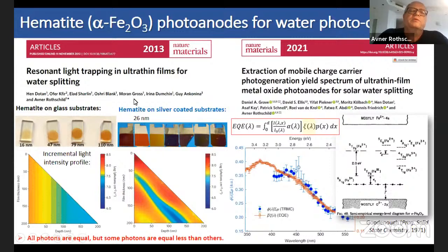So based on this concept, we've been working for nearly 10 years, and still we could not achieve the expected efficiency. The ultimate limit for hematite would give you 12.6 milliamps per centimeter squared under normal sunlight radiation, but we can only get about 4. And no matter what we did, by improving the crystal structure, by adding different selective layers, there is something like a glass ceiling that we couldn't break. So it took us a while, and then we realized that there must be another factor that works against us. And we started questioning what this factor is.